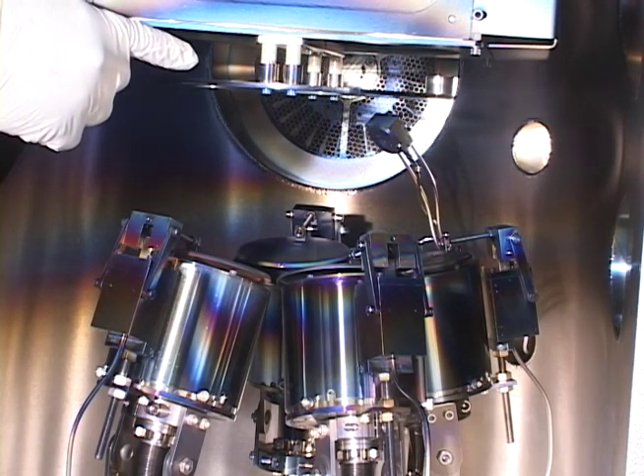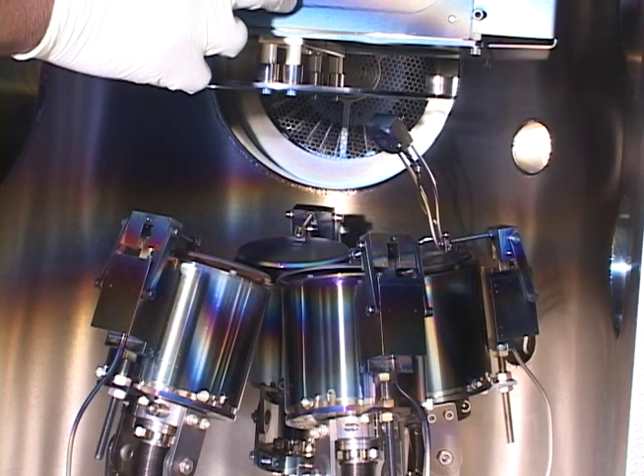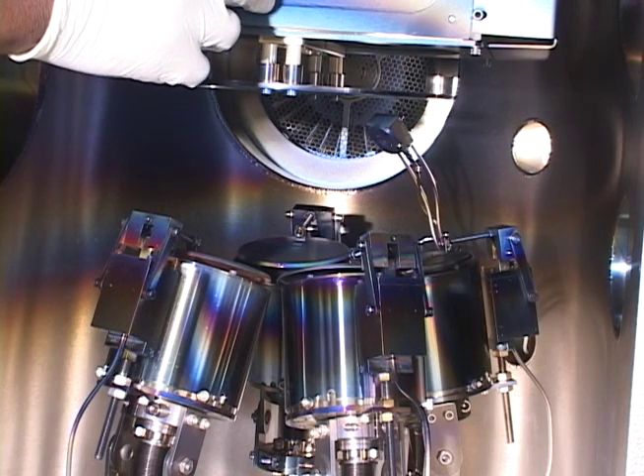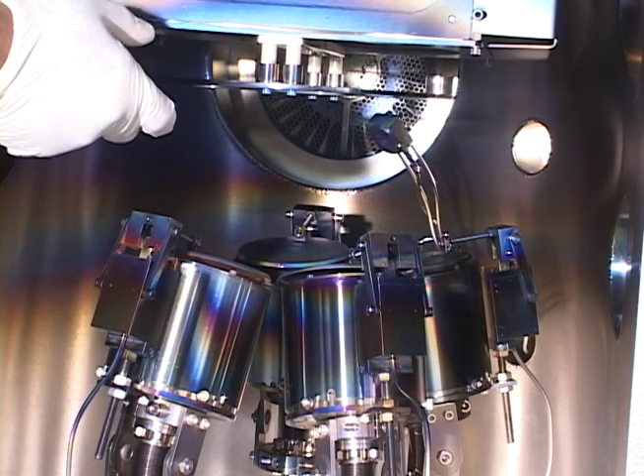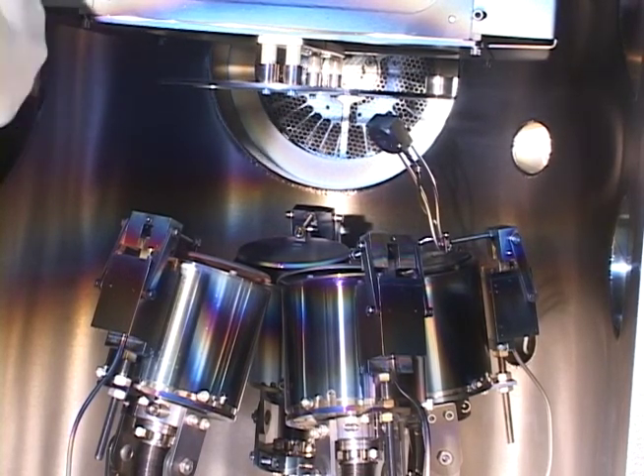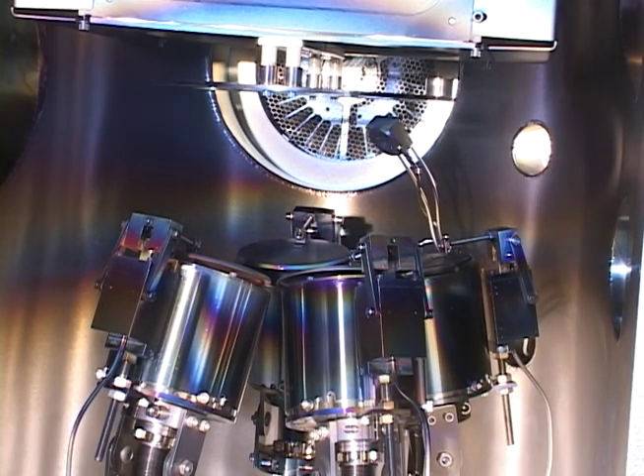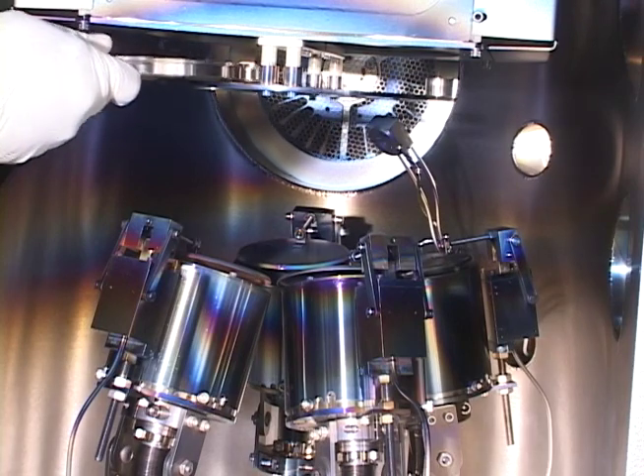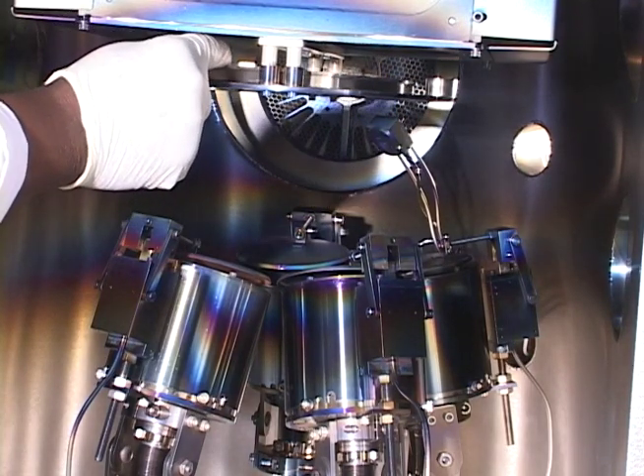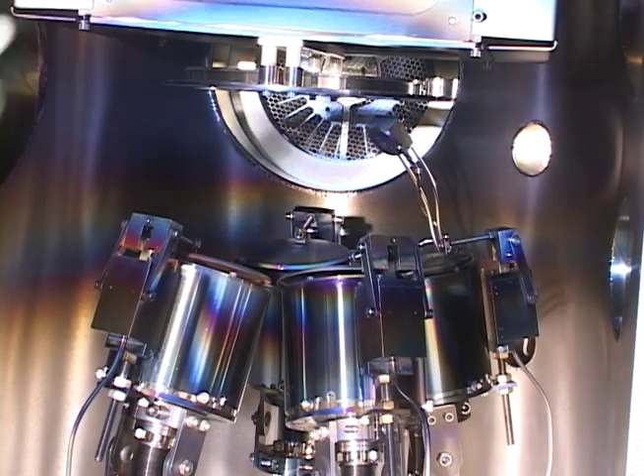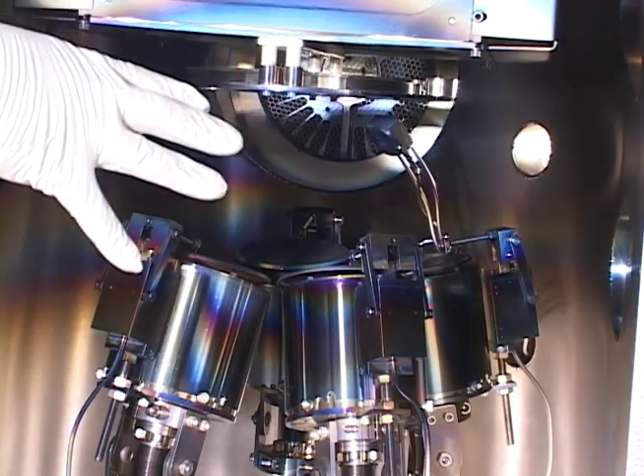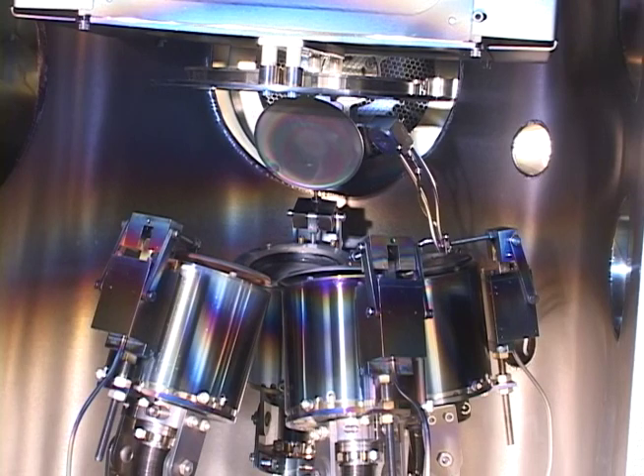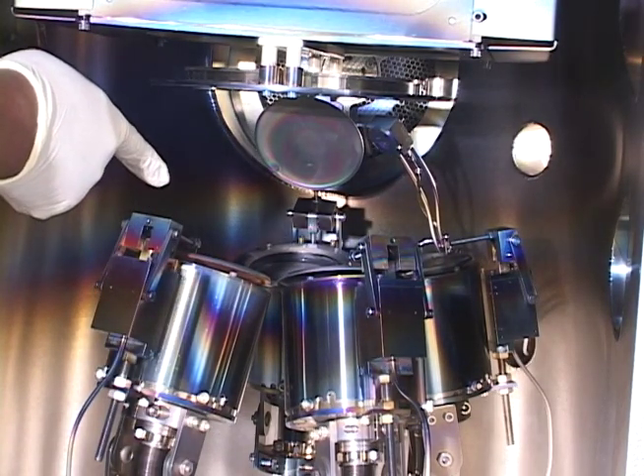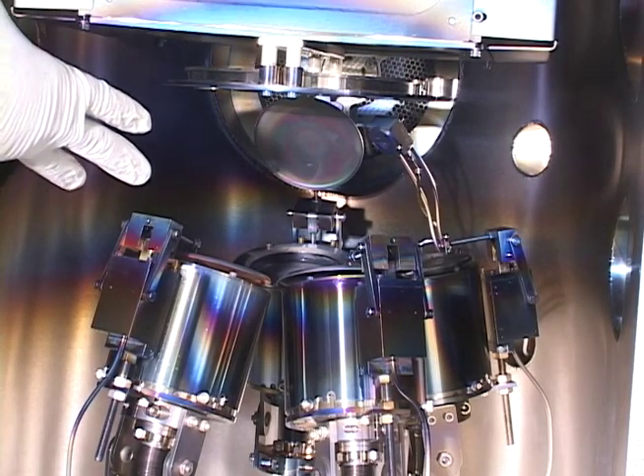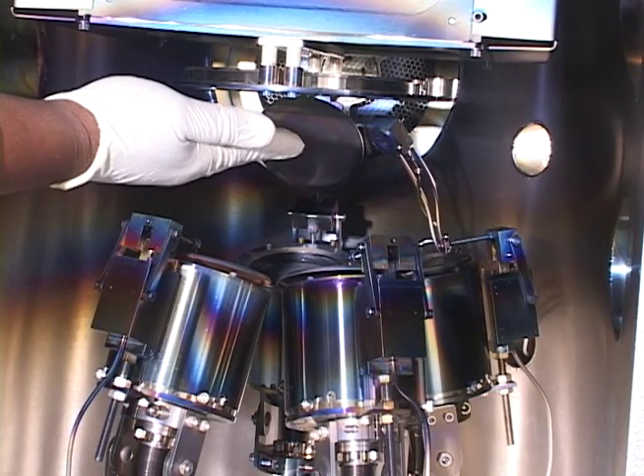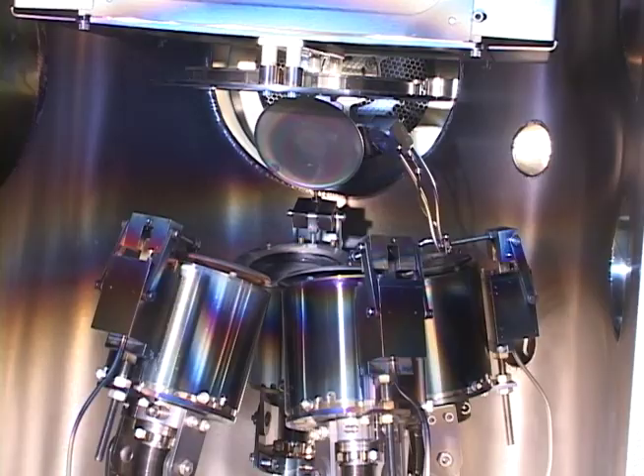As you can see, this particular component came from a 0-0 axis, or we'll call it a home reference, and we extracted this membrane all the way down to its full extent. And then you'll have a mechanical arm coming from the left side of this compartment, whereby it would transfer the substrate into this location here. Once that is done and all the operating conditions are met, we'll have this particular shutter pop open, and the plasma will take place, whereby it's going to etch the material of that target onto the substrate that's been mounted vertically above these guns.